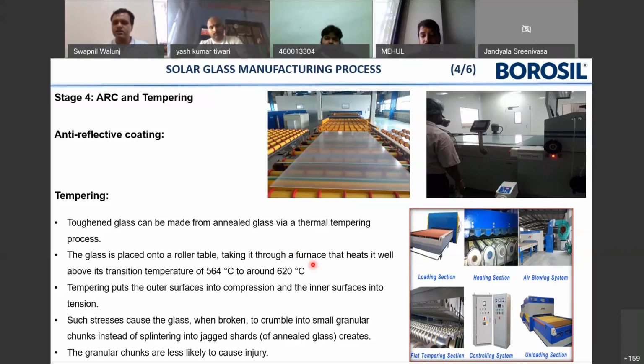This process is called tempering. Toughening is a simpler word for this. The glass is placed on a roller table, and then it goes to a chamber, or rather simply put a kind of furnace, where it heats up to a temperature of 564 to 620 degrees Celsius. The outer surface gets compressed and the inner surface gets tense, so that these stresses actually make the